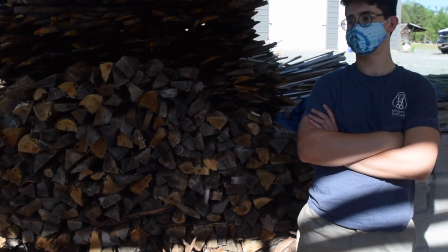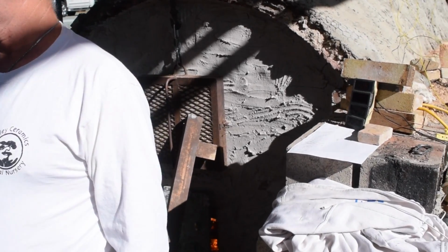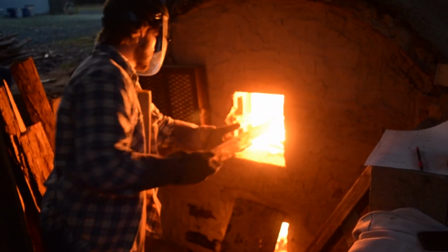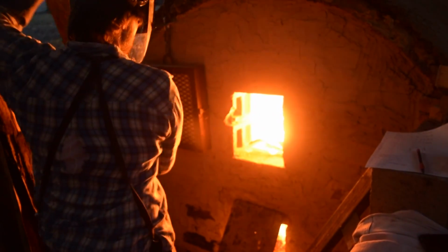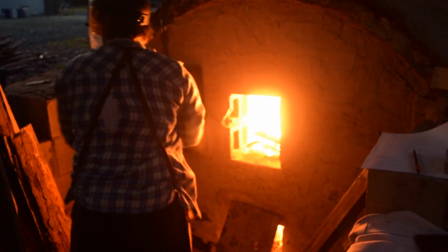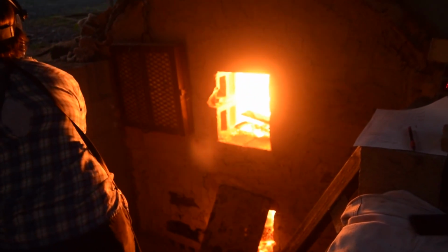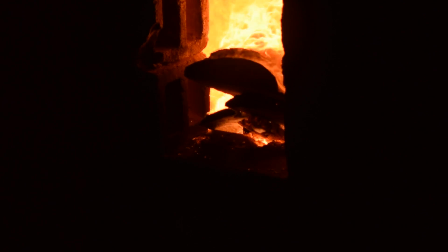Now is where the real fun begins. We start getting up to top temperature on the second day of the firing. This is in the morning, probably around 6 o'clock or so, and we're probably around 2100 degrees or so, starting to really get some cone movement in the very, very front of the kiln. At this point in the firing, it is so hot up front that we put in these giant bundles of slabs and they instantly explode when they hit the heat.